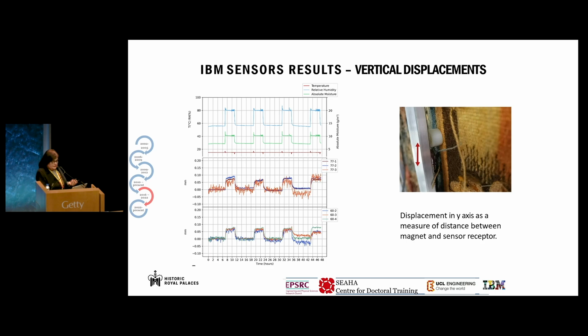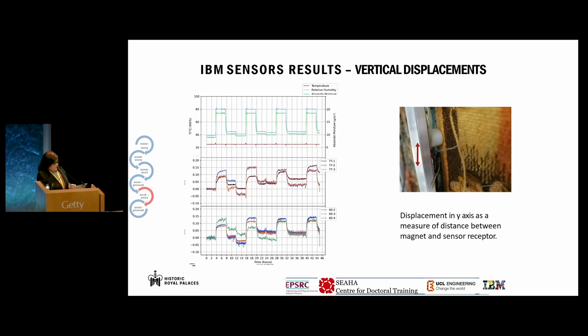In terms of magnitude, there is a change of around 0.05 millimeters as the level of RH increased from 55 to 80%. However, for the cycle at 25 degrees, the displacement increased to 0.1 millimeter. And that, again, was in line with the DIC results, and potentially we can explain it because of the absolute humidity changes. In both experiments, although most of the sensors tend to follow the same pattern, some of the displacements are slightly different, potentially due to the design differences on the tapestry.